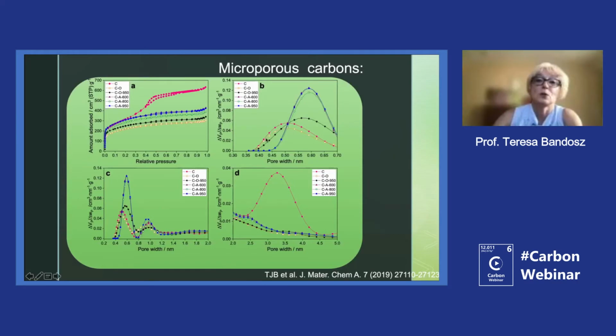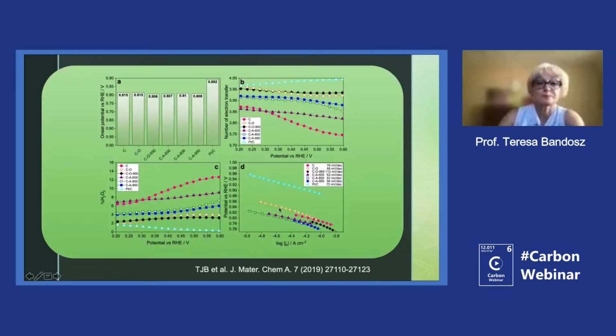And so then, once again, the result, once again, the most positive onset potential was on the samples without nitrogen, and number of electron transfer too. So as you can see, the oxidized sample was very good, and the oxidized and reduced samples were found as the best.